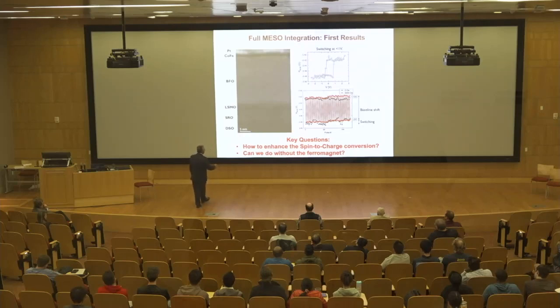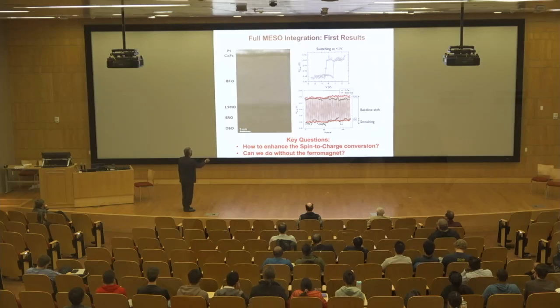Our friends in Spain actually built this structure. So we could switch the BFO back and forth with an electric field. We could read that out with the inverse spin Hall resistance, or the current that comes out of it. That resistance changes itty-bitty, but it's measurable. With the lock-in, it's not a problem. And you can see that it switches at about 500 millivolts for about a 20 nanometer thick sample. And you can keep doing it back and forth with this process.